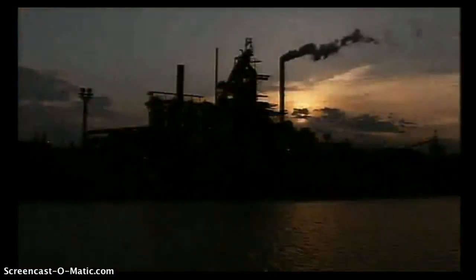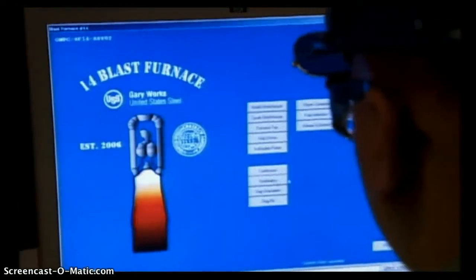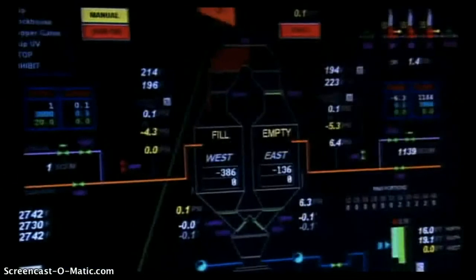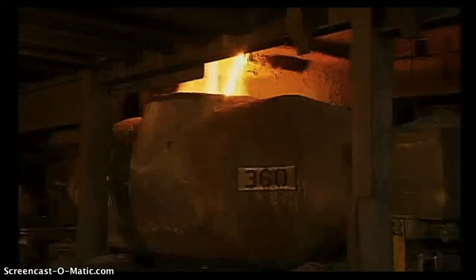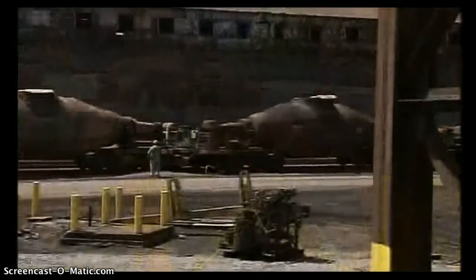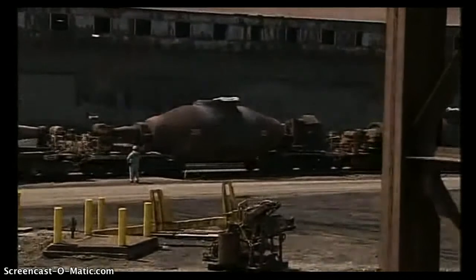From below, a continuous blast of superheated air combusts the coke, intensifying the heat and changing raw materials into molten iron. Sometimes more than 9,000 tons of it a day in our largest blast furnace, where it reaches a temperature of 2,700 degrees Fahrenheit. At regular intervals, we tap this blistering brew into giant submarine ladles that ride on rails to the basic oxygen furnace, where iron will be turned into steel.